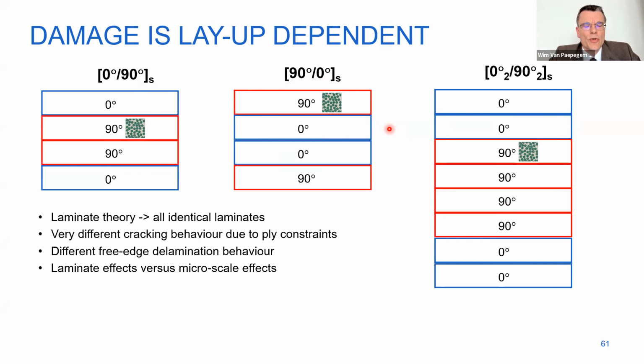About the micro scale, honestly, we see it more as getting insight into the behavior of a composite rather than trying immediately to calibrate ply-based models. The reason is that I showed you some insights into the self-heating problem. We are currently also working on, because the self-heating was still at ambient temperature, the temperature was not changing. It was just the internal temperature which changed. But we are also working on projects, especially for automotive, where thermomechanical behavior is important, where also the ambient temperature is changing and crossing the glass transition temperature, and you get a lot of nonlinearities. And trying to really have an exact prediction from the micro scale up, we still struggle mostly with the interface.